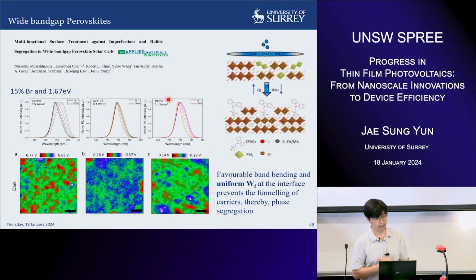but this doesn't help much in terms of phase segregation. And we performed Kelvin probe force microscopy on these materials. This is 0%, so this is the control sample, this is one where we only put 2PACz material, and this is a mix of FABr and 2PACz. We've seen that there's a homogeneous distribution in the work function. So this passivation allows you to have good band bending between your materials, and such uniform work function prevents carrier funneling between nanoscale regions. That suppresses and helps with the phase segregation.